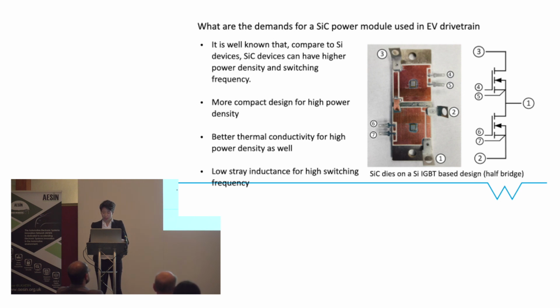And this can be achieved by using more advanced die attach technology, like silver sintering, to replace conventional solder material. And finally, we want the module to have a lower stray inductance in order to have high switching frequency. This can be achieved by optimizing the layout of the DBC, as shown here.